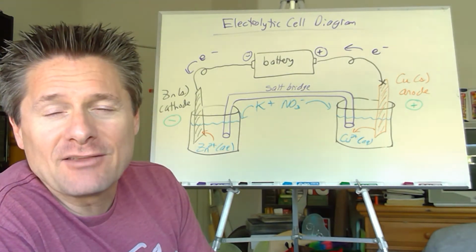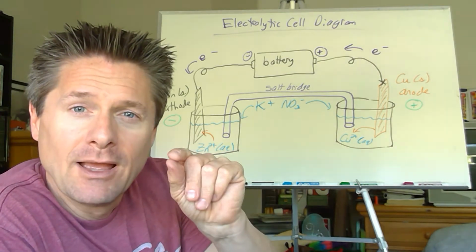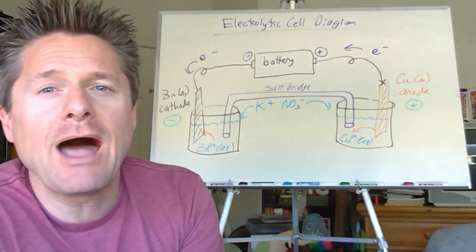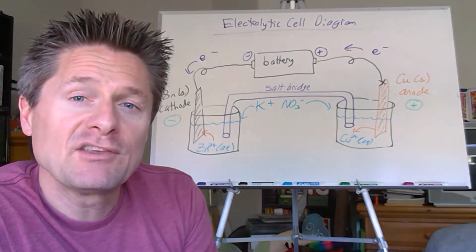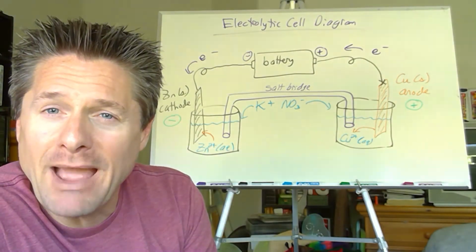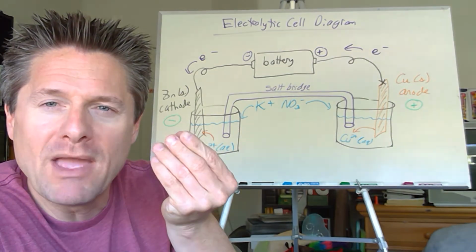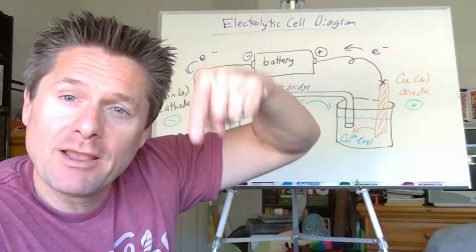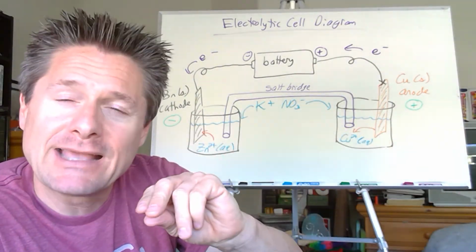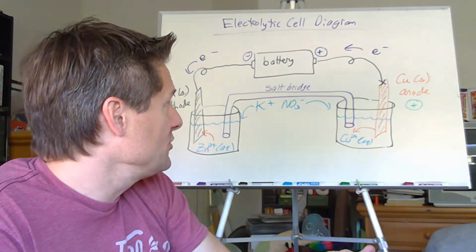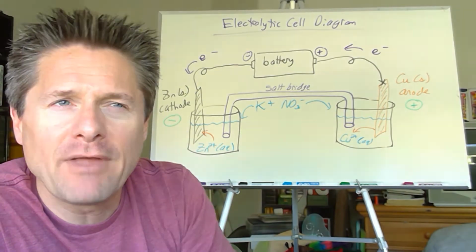I did this as one of my voluntary labs my senior year. I wanted to measure the copper content in pennies pre-1982 and post-1982. So I did the experiment twice, and I dissolved them up in some acid and got the copper ions in solution. Then I took this dry wire mesh, and I weighed it. And then I hung it in and hooked up an electrolytic cell and ran some electricity through, and then I plated the copper. So I took the copper 2+ out of solution and plated it as solid copper onto the wire mesh.